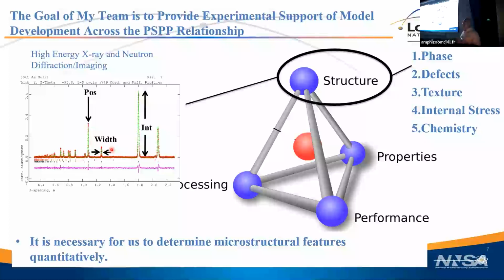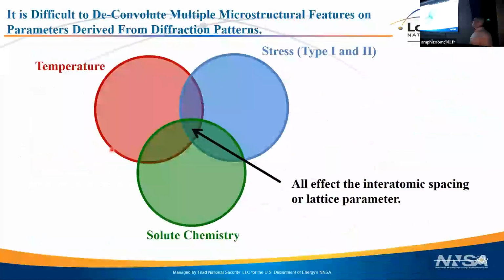In my mind, that means we're not quite ready. Maybe the ESRF is now, maybe detectors aren't, but we're not quite ready to look at in-situ powder bed fusion other than in certain ways, because the detectors aren't ready to collect the quantitative data at the rate we need. And I'll show you examples of that, where we tried to really push the limits. I will state that the measurements I'm going to show you were done about 5 years ago. So the limits are now a lot different than they were then, but the lesson is still the same: at least for our purposes, we have to make sacrifices in order to get quantitative information.